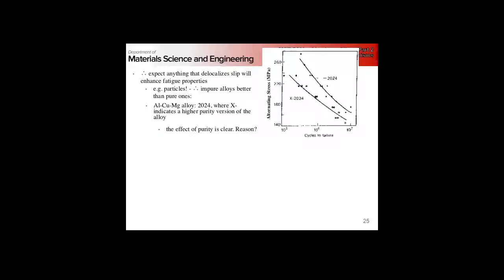The interesting thing is that impure alloys perform better than ones that are of high purity. This is aerospace alloy 2024, aluminum copper magnesium. The X designation is high purity. We see a marked decrease in the cycles to failure for a given cyclic stress amplitude as we make it more pure. So we nucleate these magnesium aluminum particles, which means that we don't have a clear slip path, so we don't form slip bands.